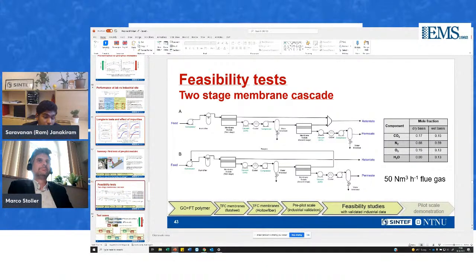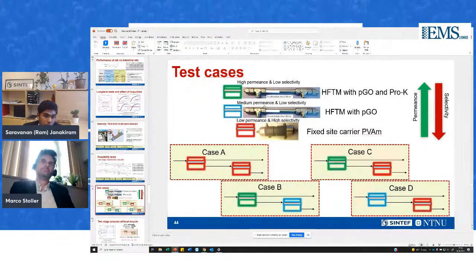But what we have done in this current feasibility test is that usually when we look at feasibility tests in membranes, many people tend to use the data from the lab, and that's normally okay. But since we had this data from the industries already, we did not take the material performance, but we took the module performance of the membranes. So this feasibility test that you see on both the stages, we have used module performances.